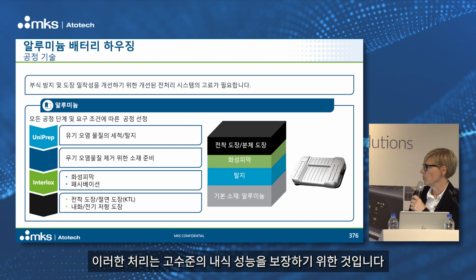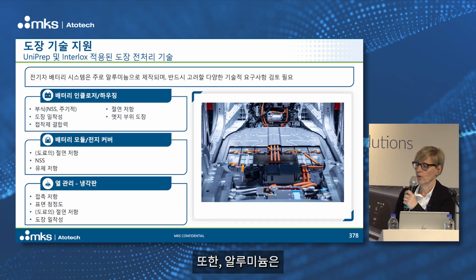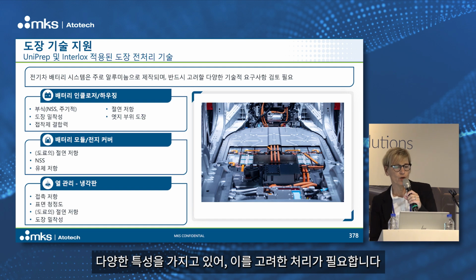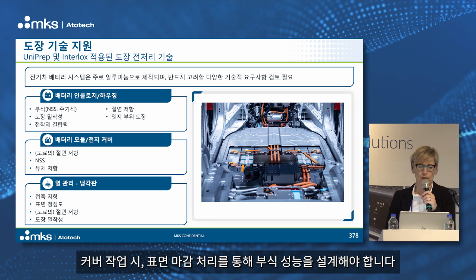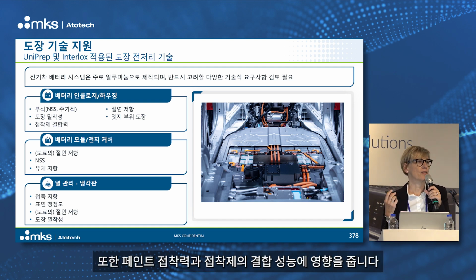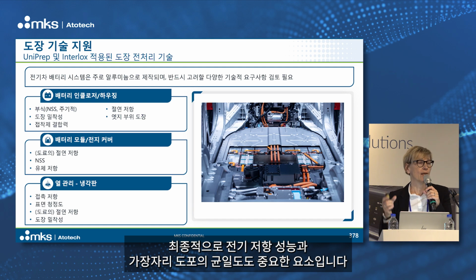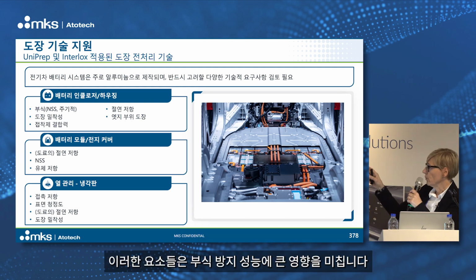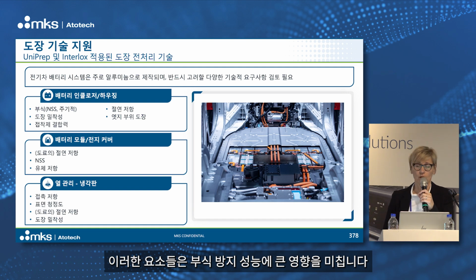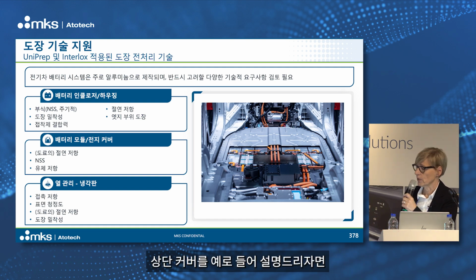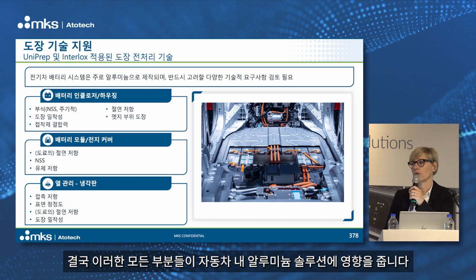And also the aluminium has a lot of characteristics which you need to influence. When you are working on the cover, you also need to expect that with the surface finish, you are also designing the corrosion performance. You are influencing the paint adhesion, you are influencing the adhesive bonding afterwards, also the dielectric resistance at the end, and the edge coverage is also important in corrosion protection later on. If we are just looking into this upper box, at the end, all this is influencing the aluminium solutions in the car.